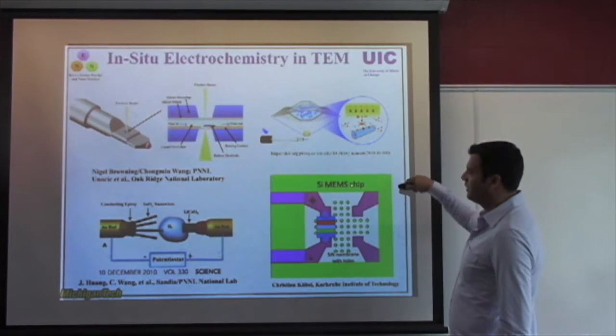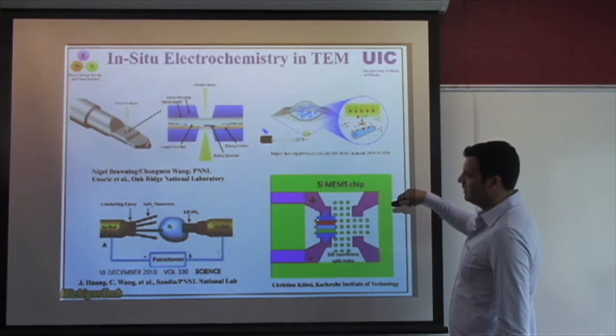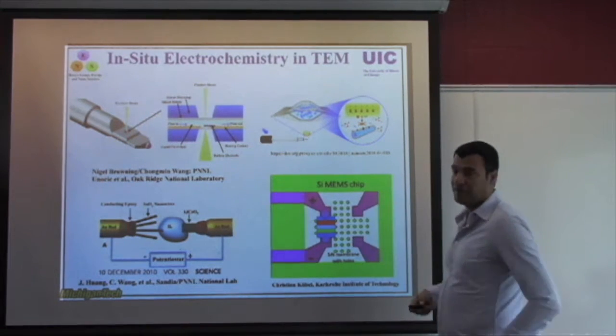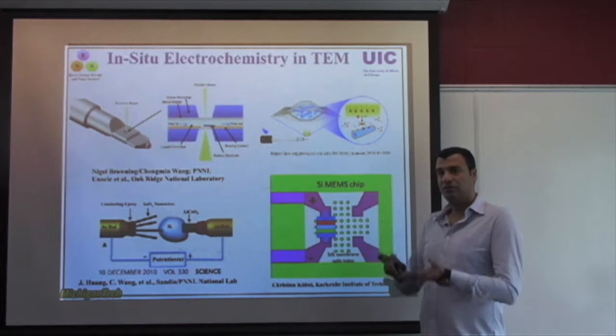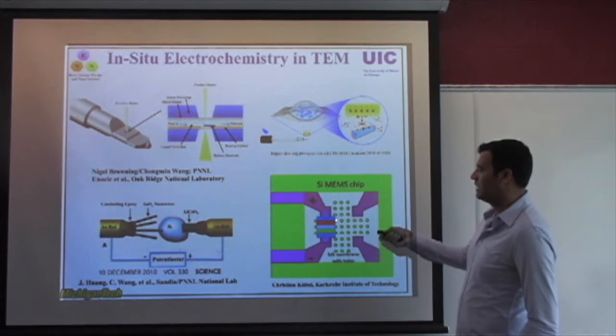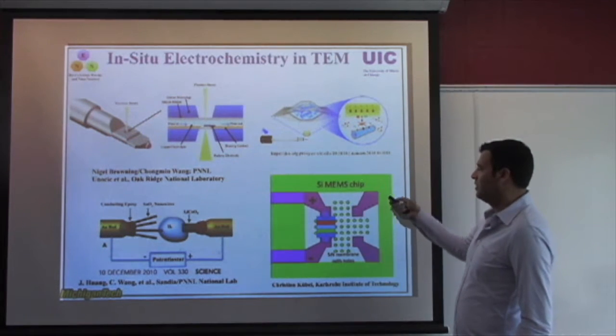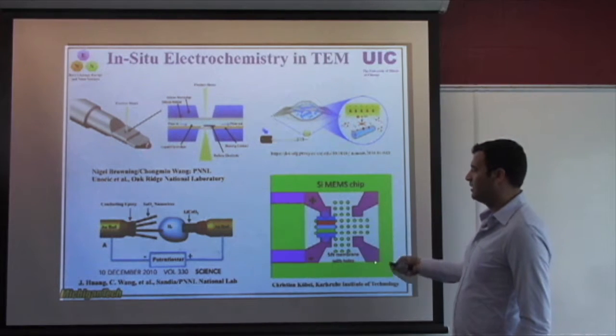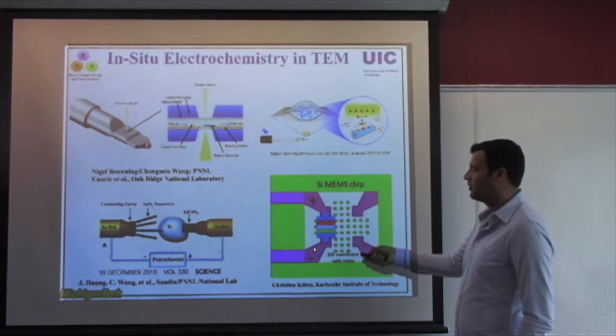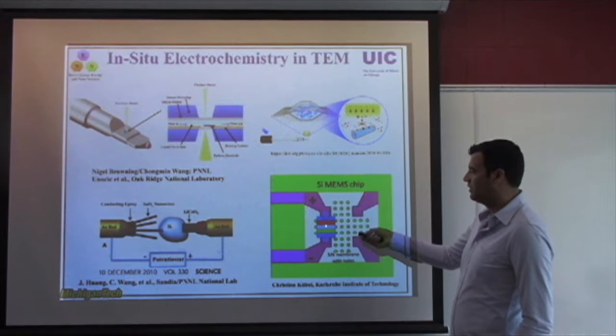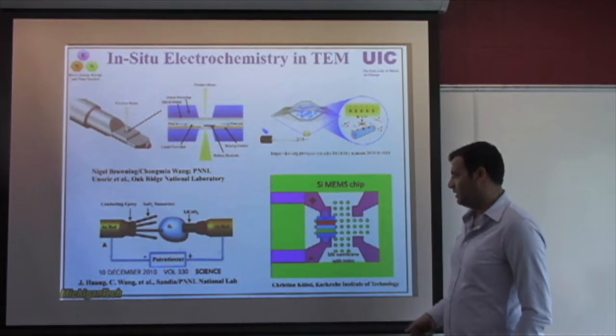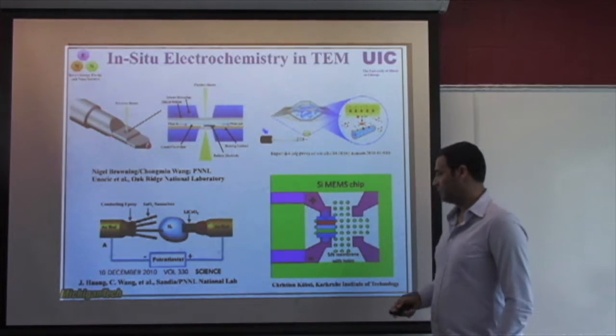And this is another work where you can basically prefabricate the thin film of the battery, do the FIB cutting, and put the sample on one of these membranes, silicon membrane, and then apply a potential, and then look into what's going on at the interfaces or at the electrodes or electrolytes itself.